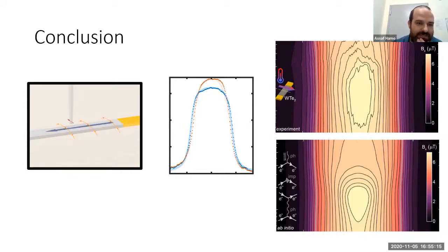It's a compensated semi-metal. We think we know this because when you try to measure the Hall voltage, it is almost zero. So it means the number of electrons and holes is almost the same. So you have pockets of electrons and holes together.